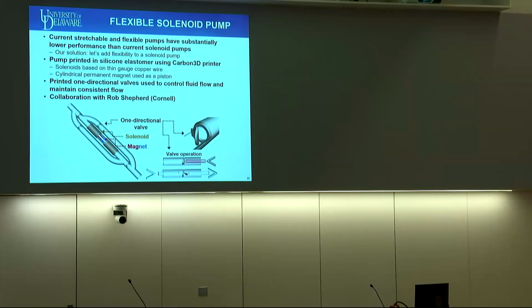Basically we'll be printing this pump within a soft elastomer using a type of specialized SLA technology called the CLIP process from a Carbon 3D printer, where we're going to print the bulk of the material in this soft silicone and then create a solenoid based on, in this case, a thin gauge copper wire. So a flexible but not fully stretchable material.